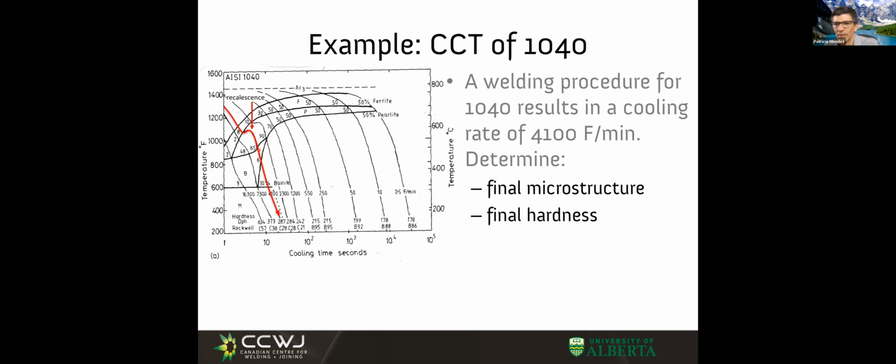Okay. Why does this effect not occur? When you have a transformation, these transformations have an amount of enthalpy associated with them. So if very little transforms or the transformation involves a low enthalpy, you don't see that much of a change. The biggest jump we see here is for two reasons. One is we're transforming a lot of austenite into pearlite.